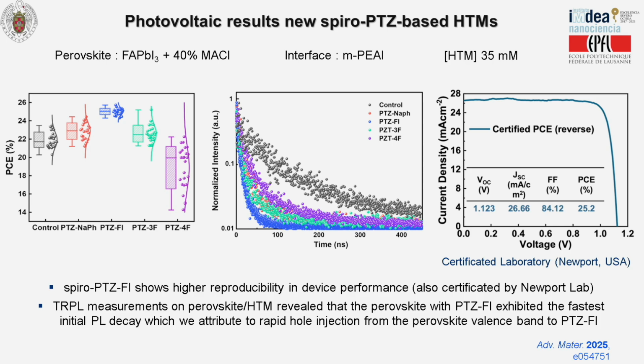But if we go to the durability and stability, you can see this is again in blue, which is the fluorine-containing compound. So this is the efficiency of very high reproducibility. And this was also certified by an independent laboratory, and you have here the result. The certified value resulted to be 25.2. This is really amazing. It's very high, one of the highest reported that I will show you. This can also be accounted for according to the time-resolved photoluminescence for this material, the blue one, which was our champion system.